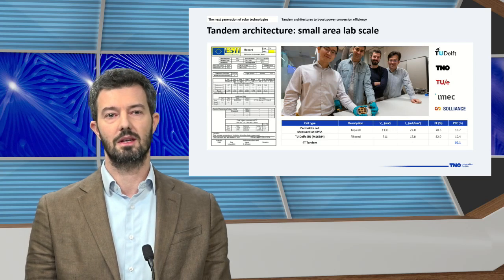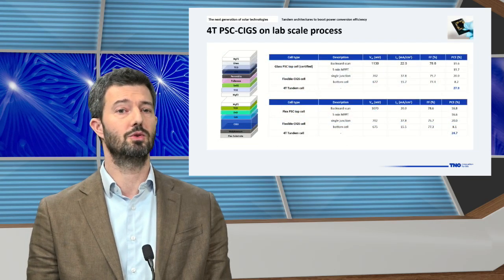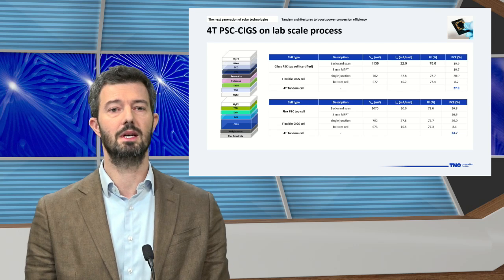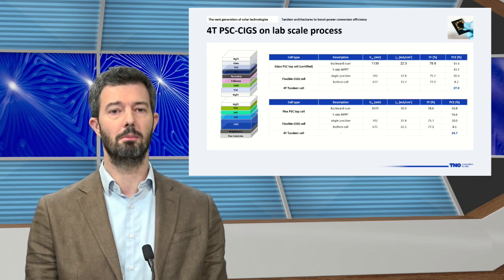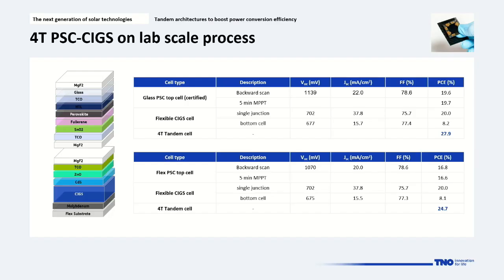So now the 4-terminal architecture can also be used for different types of bottom cell. In this example, we combine the same device that we just presented with a flexible CIGS with an initial efficiency of 20%. And what you see from the top part of this table is that the efficiency jumps to 28%. So we have a boost of 8% with respect to the single junction device. This is remarkable, and I think the highest efficiency reported up to the last few months.